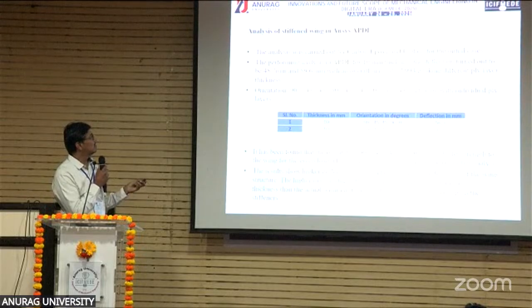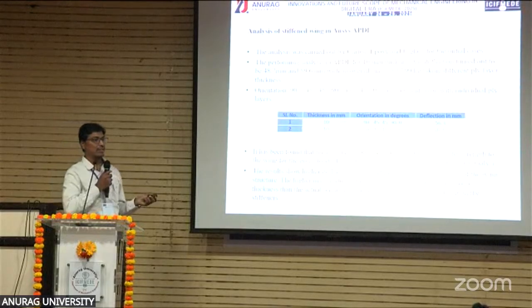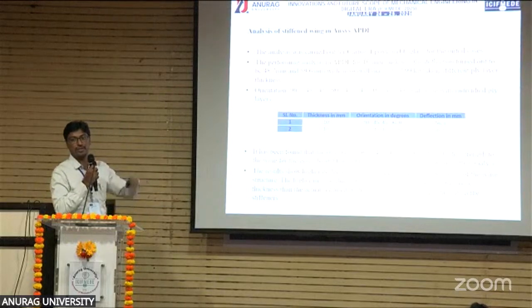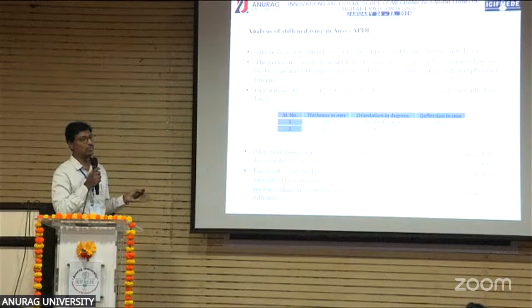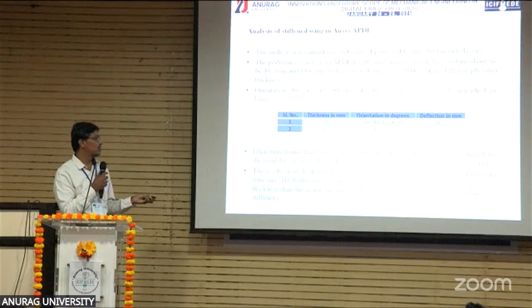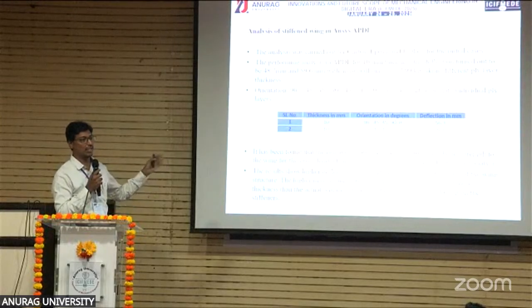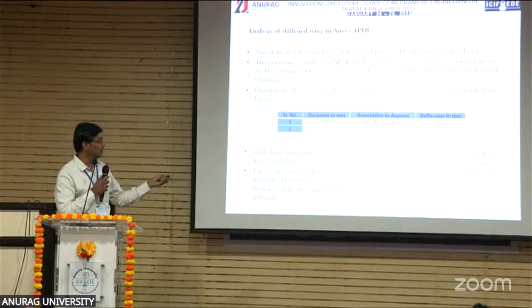Now coming to the ANSYS stiffened wing with APDL. Here the analysis was done with 10 mm thickness, as I mentioned. In APDL, initially the model with the stiffeners and the top and bottom plates was considered as a single model, so the higher mass was considered. The results showed a higher deflection than the standard due to the higher mass of the wing structure. The higher mass is because the stiffeners gain more thickness than required, due to the excess ply layup on the stiffeners. That was the condition observed in the initial APDL studies with 10 mm thickness.